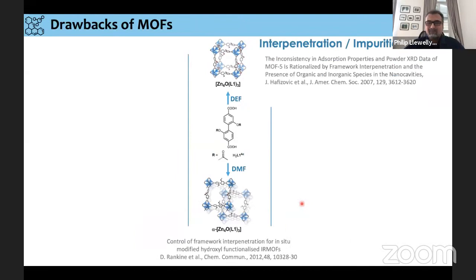So MOFs aren't great. There are many drawbacks, and I'm going to talk about three here. The first is the problem of interpenetration. So again, this is our famous MOF 5, and this is a specific form of MOF 5. If we make it under these conditions with the solvent known as DEF, we can have this quite nice material. But if we make it in the DMF, for example, we can see here that we've got two interpenetrated structures, which can lead to variations in pore size and other problems.